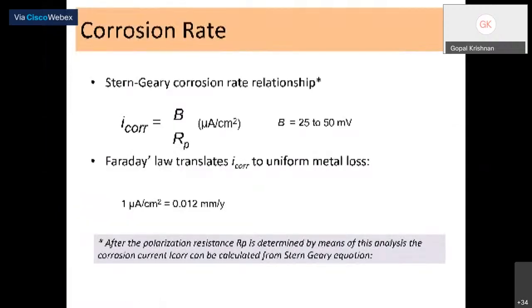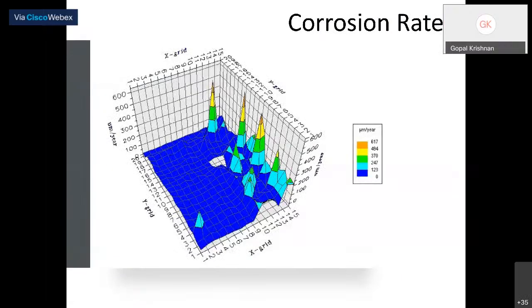The Stern-Geary relationship curve we are able to see here. So 1 microampere per centimeter square is equal to 0.012 mm per year. This is what we can get from the Stern-Geary equation relationship. We can use contour mode to see which is the representative corrosion, which is severe and which is acceptable, with the different colors here.